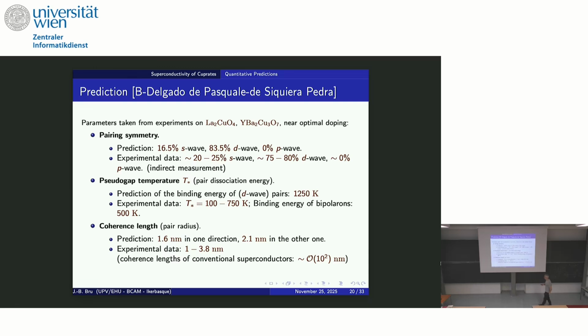Okay, so maybe I should stop. Let's just finish by saying that you get this binding energy, and for coherence lengths you get very good agreement with experimental data: 1.6 nanometers, 2.1 in another direction, and the experimental data is between 1 and 4 nanometers. So it's very accurate. I agree it's a caricature, but it gives a very good outcome, even quantitatively.